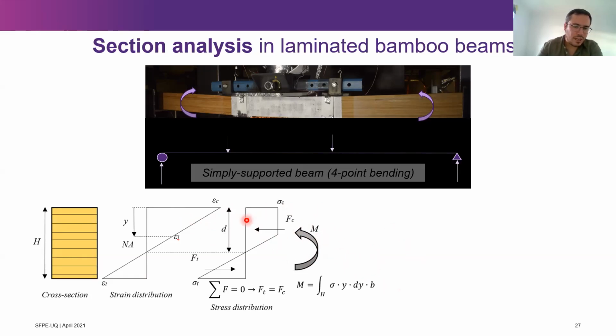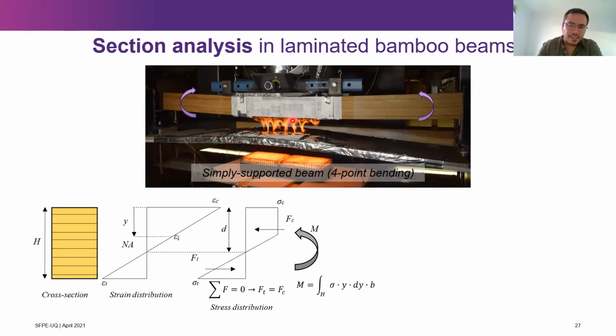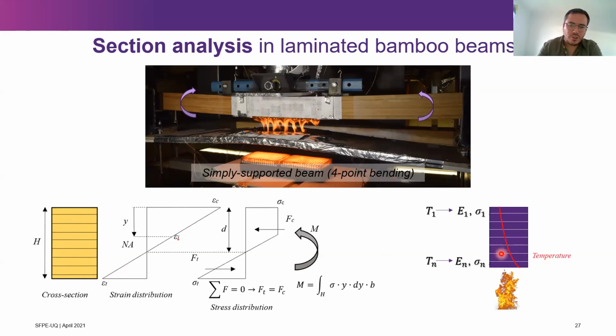The good stuff here is that you can use stress strain models, so you can predict the plastic zone. And as we know in timber and in bamboo, when we have tensile failures, we usually reach the yielding in compression, and obviously we can have better prediction for the bending capacity. The difference here is that once we expose this beam to a fire, the properties of our cross section are not constant anymore, right? Because we are going to have a temperature distribution.